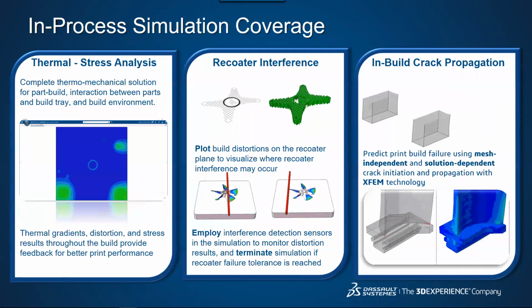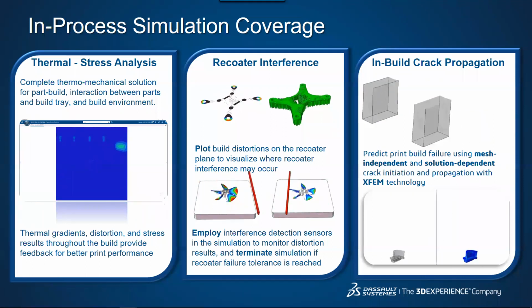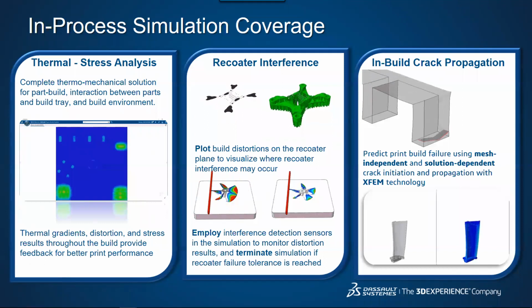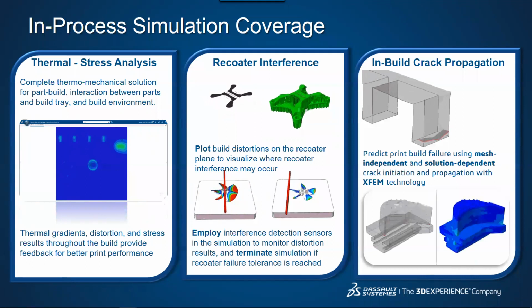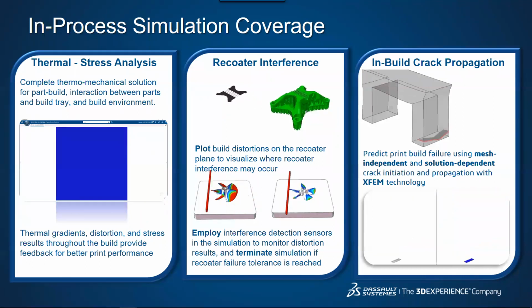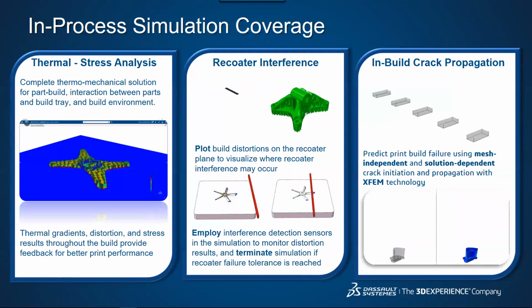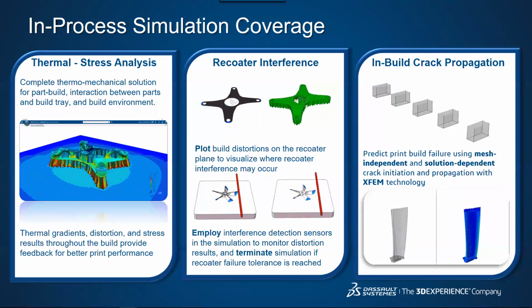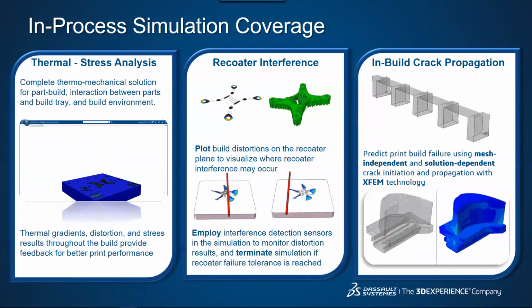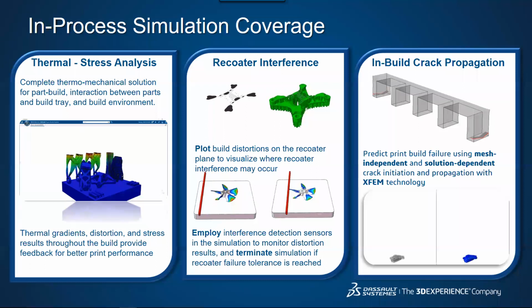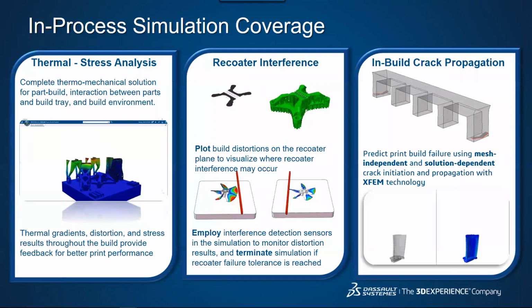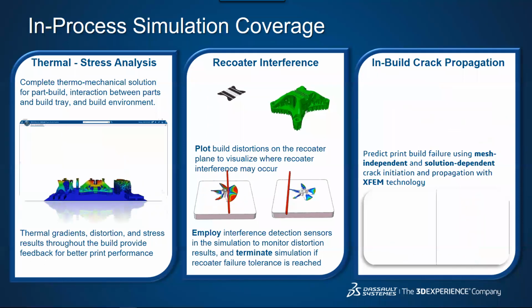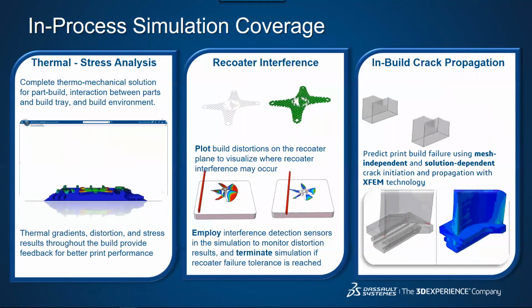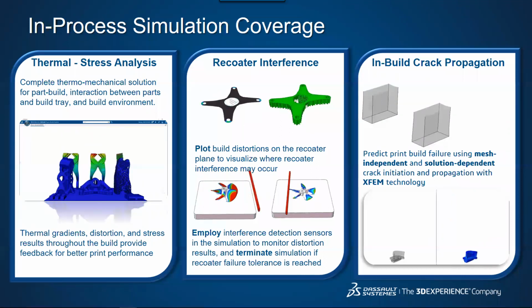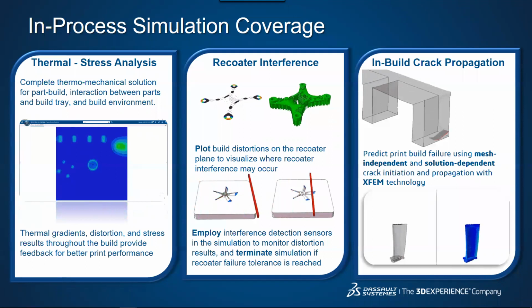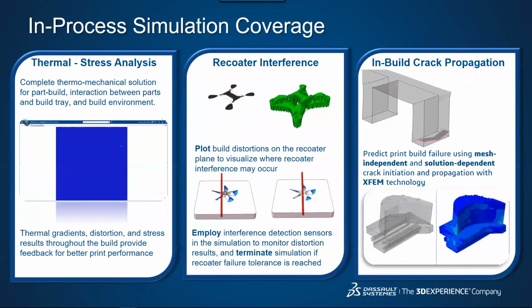Let's look now at the value that these process simulations can provide. Working with different customers, we found that recoater interference is an issue, and this occurs when distortions cause the build part to rise up out of the powder bed. This interference can cause defects, porosity, or it can completely kill the build. To examine recoater interference, we can do a couple of things. Either we can monitor the distortions during the build on the current recoater plane, and check that these values are within a given tolerance, which is what's shown in this animation here. Or we can monitor those distortions during the simulation, and then terminate the simulation once a failure tolerance is reached.